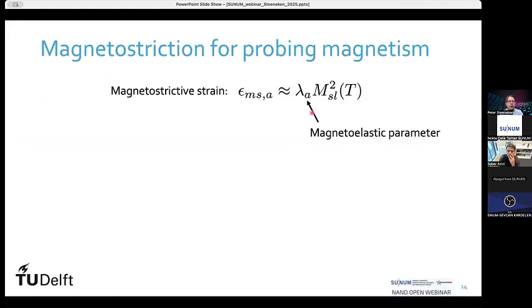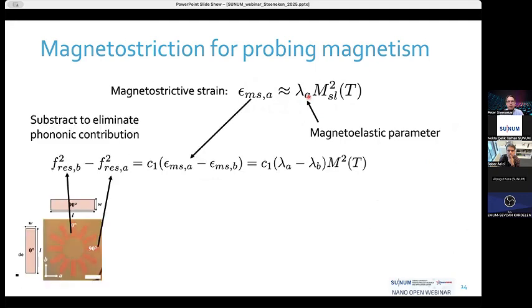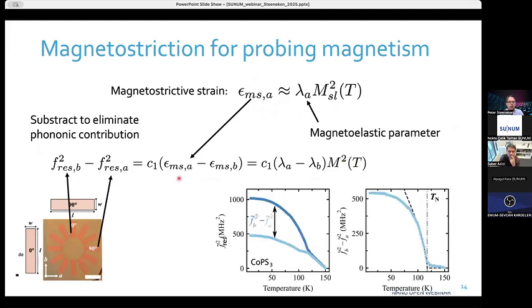Well, it's known that this kind of expansion due to this magnetic order is given by a magnetoelastic parameter. So we can relate this strain and stress that occurred to the magnetization of the material. And these magnetoelastic parameters are then depending on the direction in the crystal. And if you do some math, you can actually relate the resonance frequencies to this magnetization, and we can extract this magnetization curve. So that's what we did. So we take the difference of the resonance frequency squared along the two directions, so for the 0 degree and the 90 degree, and then we get a curve that is related to the magnetization squared. And that's interesting because getting the magnetization close to this Néel temperature is very interesting and hard to do with other methods.